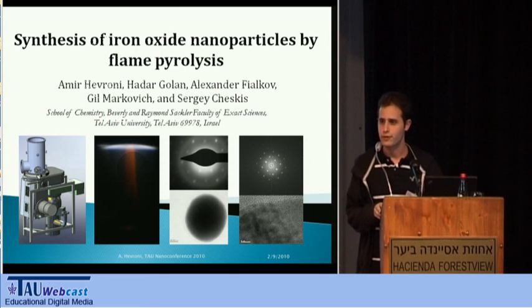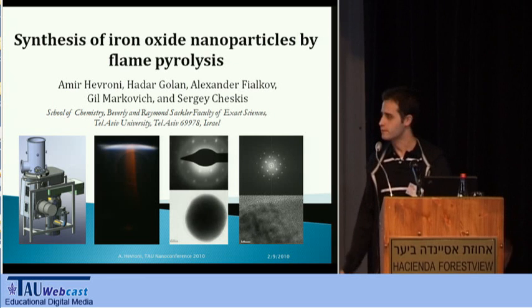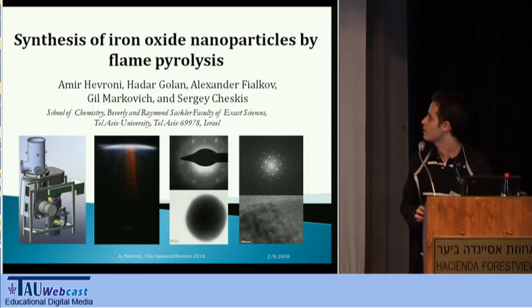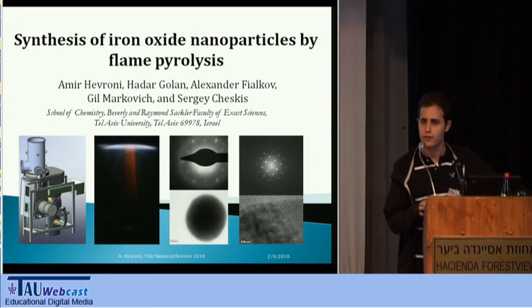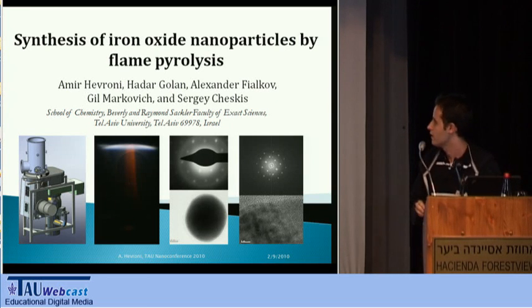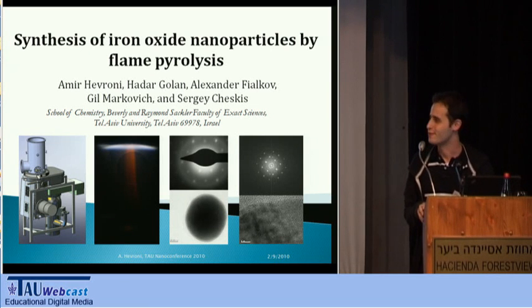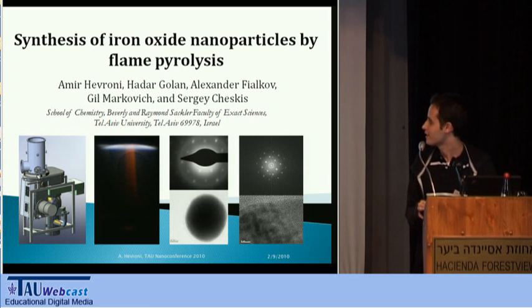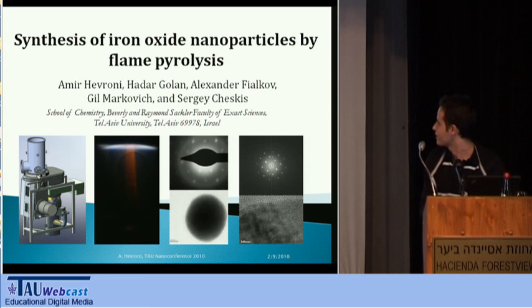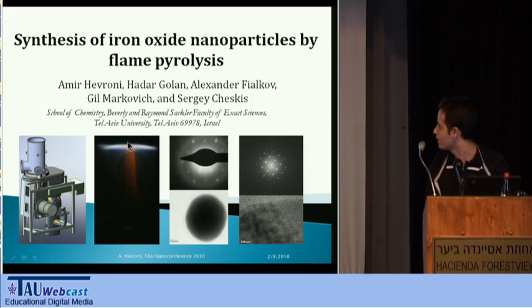Hello, my name is Amir Hevroni. I'm from the research group of Gil Markovich, and I'm here to present this collaborative project between the Markovich and the Cheskis group. We're working on synthesis of iron oxide nanoparticles at the moment. For that purpose, we have developed a very complicated system which involves a low-pressure combustion chamber. Into the center of the flame that we form, as you can see in the picture here, we inject nebulized precursor solution. We're currently using iron chloride.